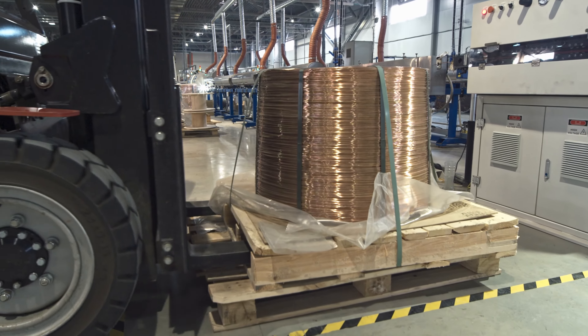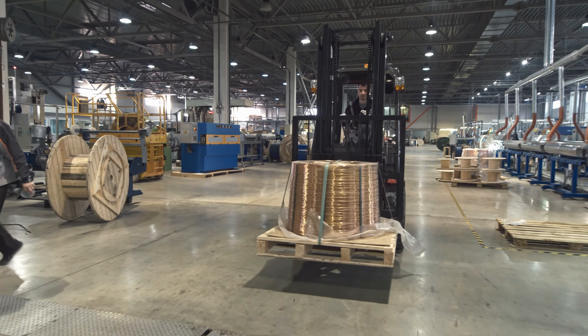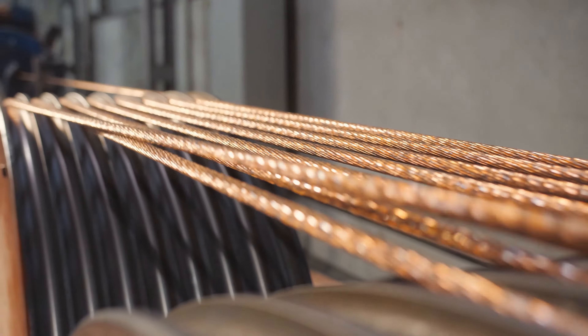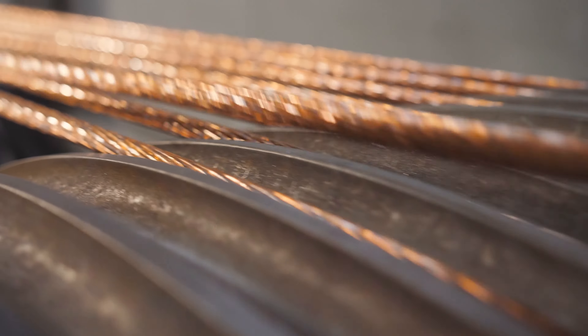Air pollution can also cause copper cables to corrode. Pollutants such as sulfur dioxide and nitrogen oxides react with copper to form corrosive compounds. Hydrogen sulfide is considered one of the most corrosive atmospheric pollutants — a weak, diprotic, reducing acid, readily soluble in water and dispersed into the air by winds. When emitted from natural, industrial, and anthropogenic sources it impairs human health and environmental quality. It attacks copper, forming a thin film of metallic sulfides or dendritic whiskers, which are cathodic to the metal substrate, enhancing corrosion. This formation of non-conductive films can lead to catastrophic electrical failure.